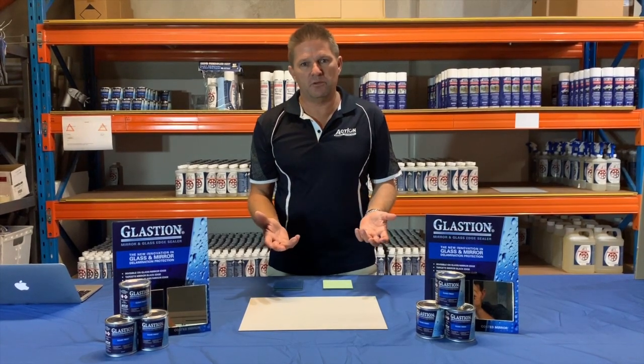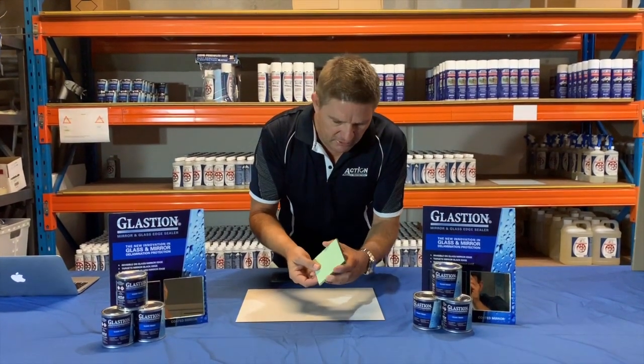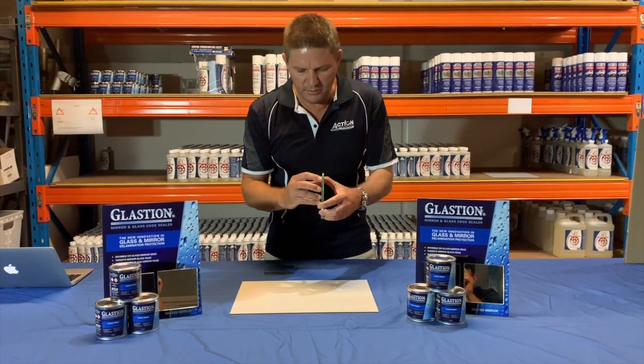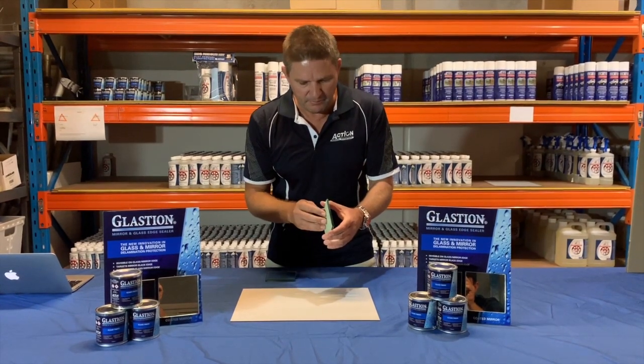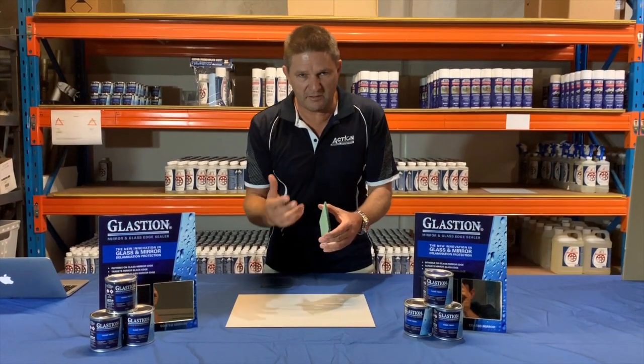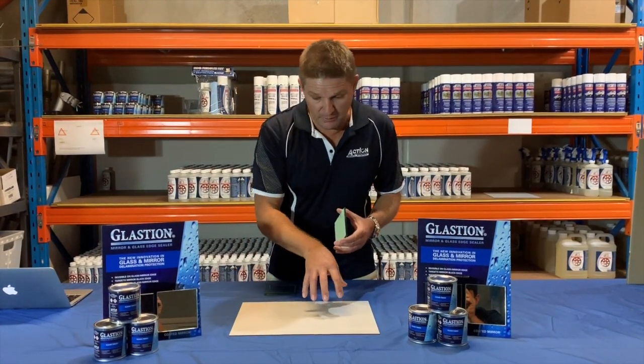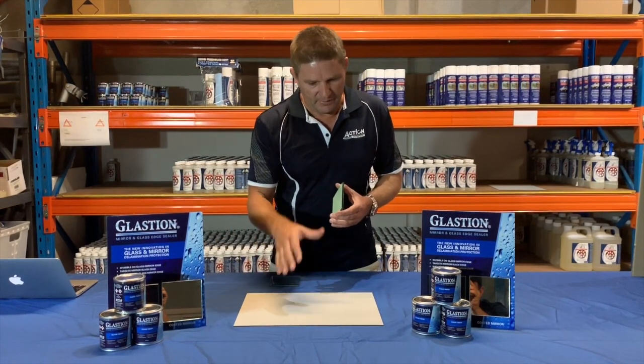It's a very unique product. Experts and contractors in the glazing field have reported that incidences of mirror black edge are more common these days. The mirror backing used to consist of a foil layer, then a thin layer of copper, then a top coat — essentially three layers. Today's mirror manufacturing has moved to just a thin foil layer and a top coat, so there's less protection. That's why we're seeing more incidences of black edge on the outside and also delamination on the back of the mirror. It's important to protect that sharp edge from bathroom humidity but also to coat the back of the mirror.